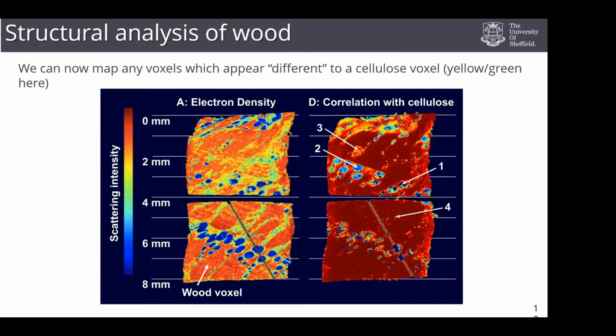We've basically mapped onto this the structure of wood, and we've located everywhere in this sample that correlates very, very highly with the wood or the cellulose structure. Anywhere that isn't red, therefore, does not correlate well with cellulose structure and is something else, something different. So, for example, this region here, that's a pore. That shouldn't be wood at all.